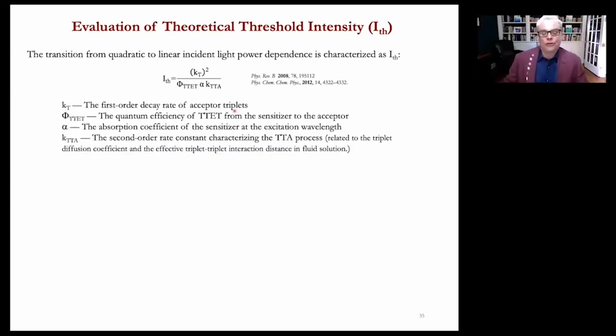To get into the details a little more, this is, again, Monguzzi's treatment. And then there's been some refinements from Tim Schmidt's group. But the idea really is the I value, to a rough approximation, and this is a very rough approximation, take this with a grain of salt, is related to the triplet decay of the acceptor and the bimolecular triplet-triplet annihilation rate constants. So those are fixed in our experiments. And then alpha, which is really the absorption coefficient of the sensitizer at the excitation wavelength, that's also fixed in our experiments. So this is why we varied the efficiency of the triplet-triplet energy transfer reaction. That's the one parameter we could readily control.